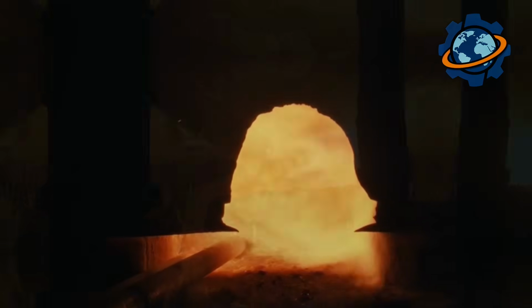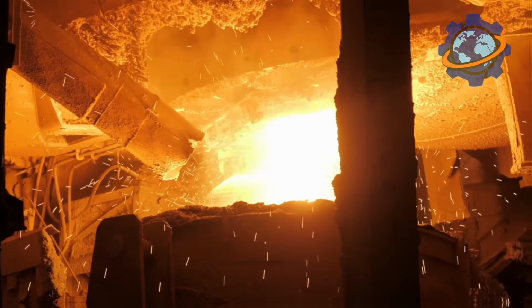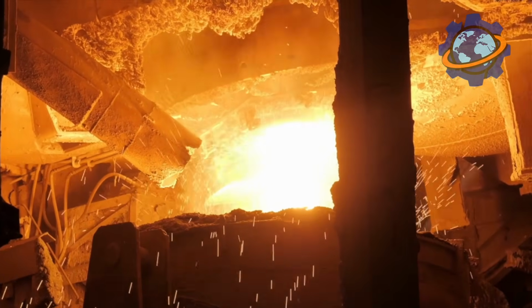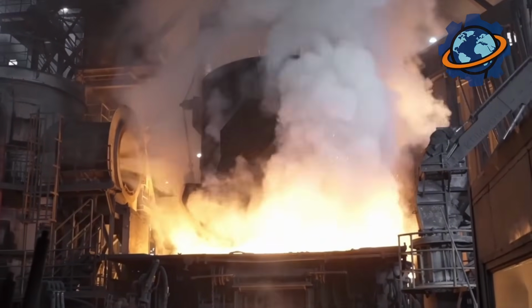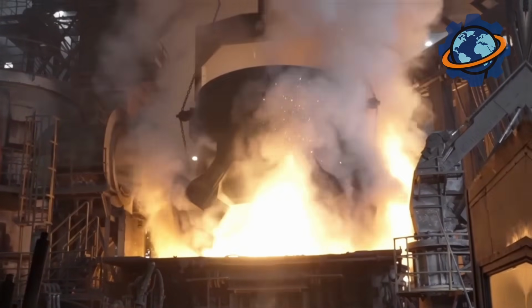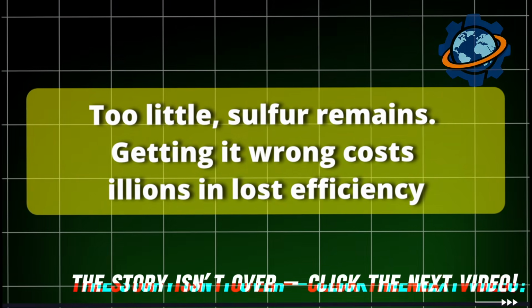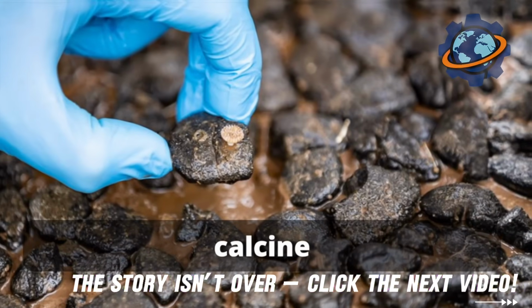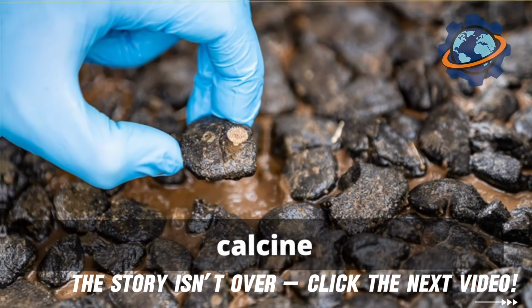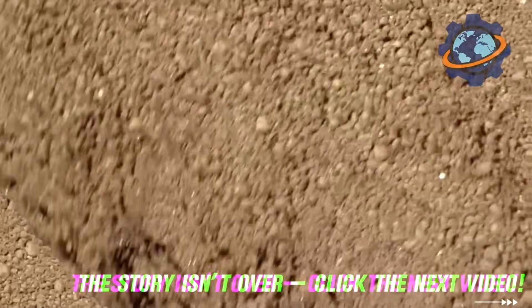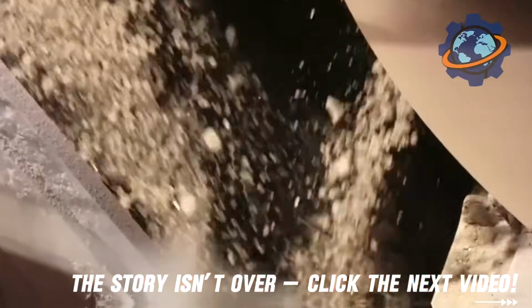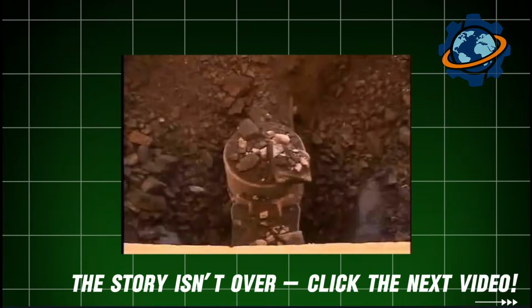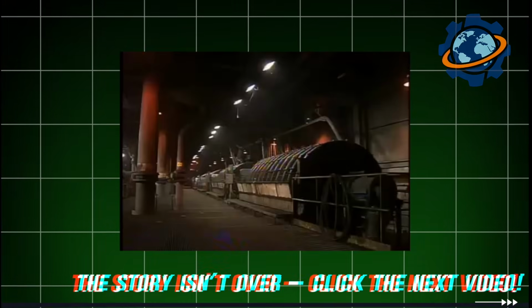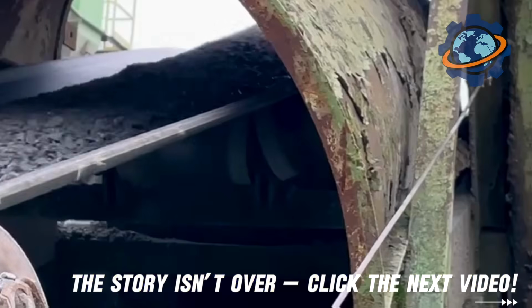Watch the roasting process through observation windows. Yellow flames dance over tumbling ore. Operators adjust oxygen flow constantly. Too much air, lead oxidizes excessively. Too little, sulfur remains. Getting it wrong costs millions in lost efficiency. The roasted material, called calcine, moves to smelting via enclosed conveyor belts. Nothing touches open air. The paranoia about containment isn't regulation theater, it's survival. Lead contamination cleanup can bankrupt companies.